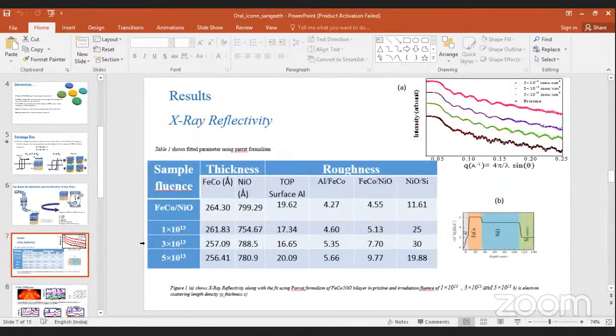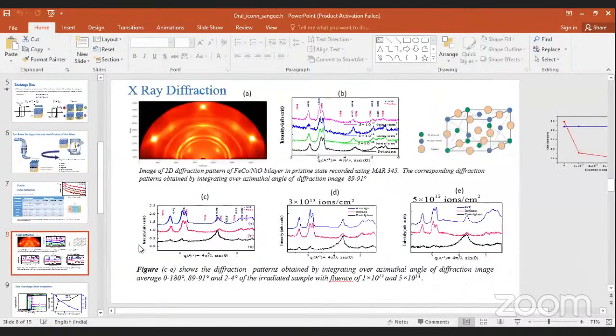Going to the results, we can see that after the irradiation, the interface roughness has developed, which means that the pinning centers have been enhanced or developed in this system. This roughness enhancement at the interface contributes to the coercivity enhancement, which will be discussed in the magnetic studies. For structural characterization, we performed 2D image plate measurements using the MAR345 facility, and we see that the stress induced during the deposition has been relaxed after the irradiation.